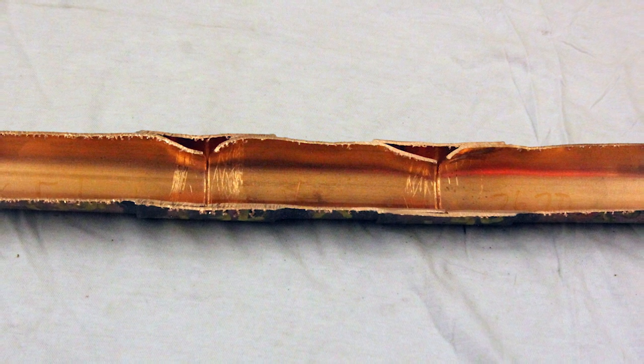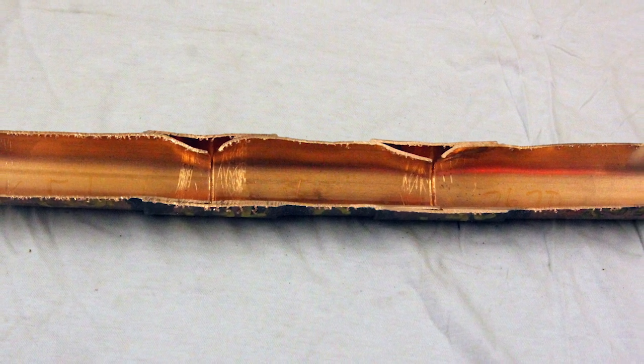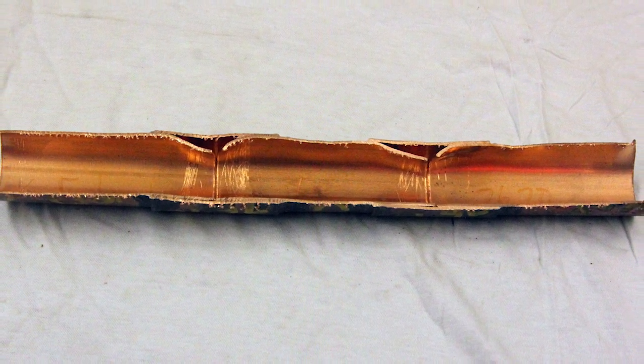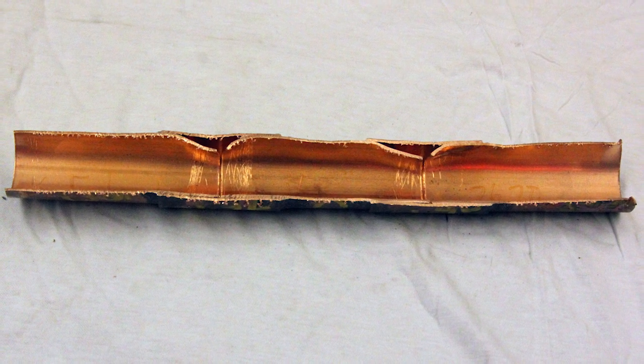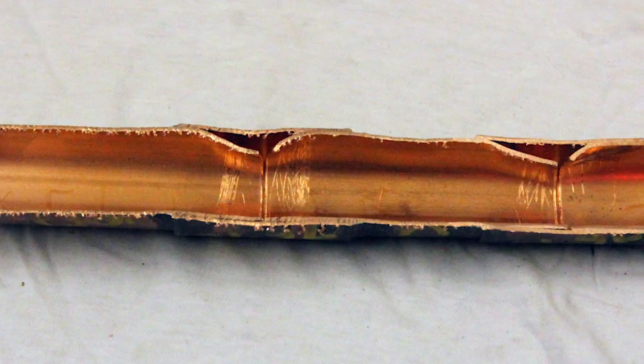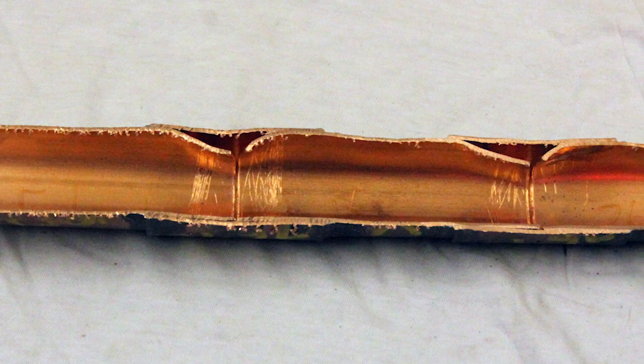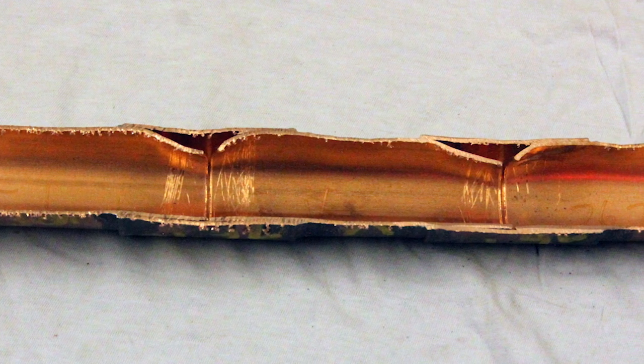ASME Section 9 states, each side of the specimen shall be polished and examined with at least a 4-power magnifying glass. The sum of the length of the unbrazed areas on either side, considered individually, shall not exceed 20% of the length of the overlap.